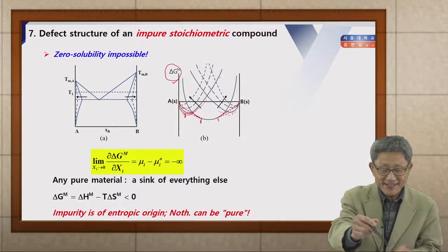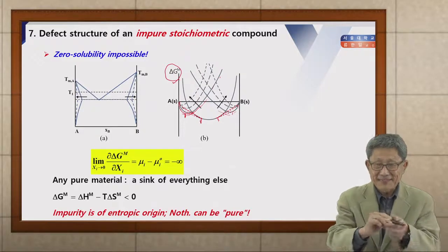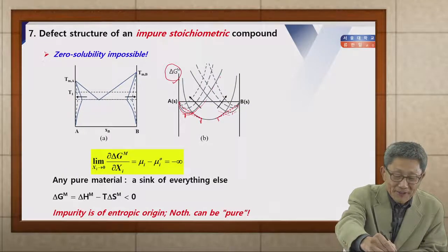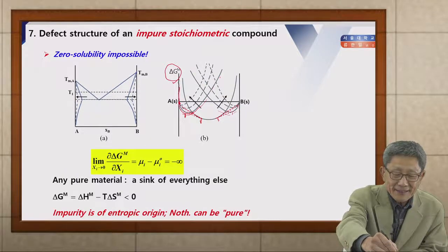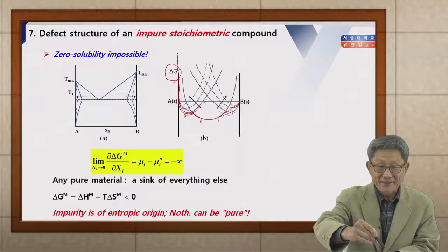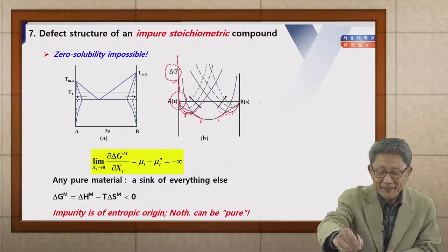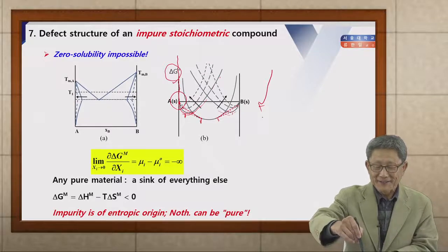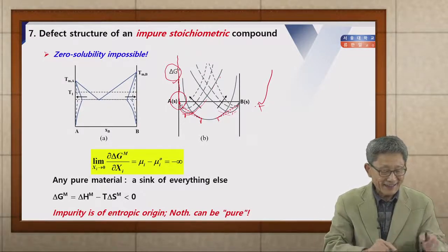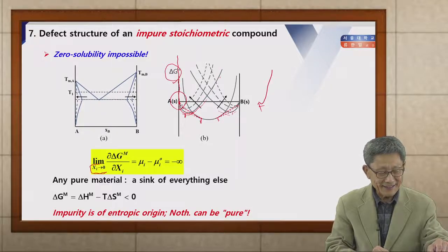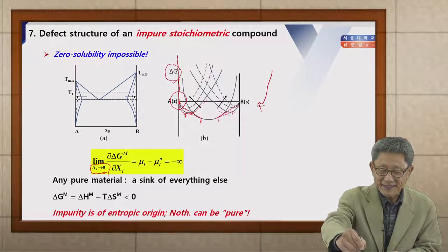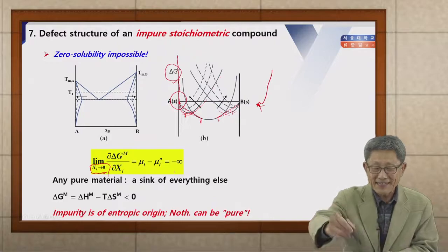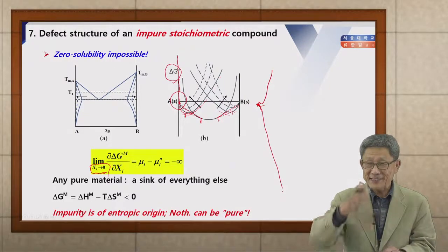As the solubility decreases, this mixing free energy curve is getting narrower and narrower, but still, don't forget, eventually it looks like just this component axis. But if you expand this part, it still has this kind of minimum, okay? So if you take the slope at this composition axis, then you end up with the slope of minus infinity. Actually, such a minus infinity slope.